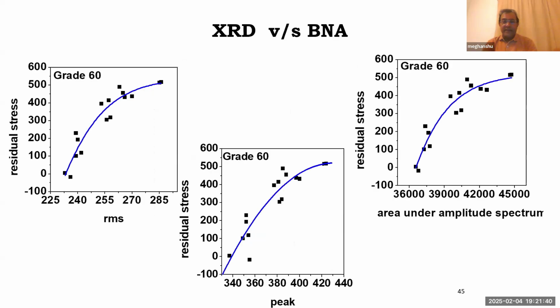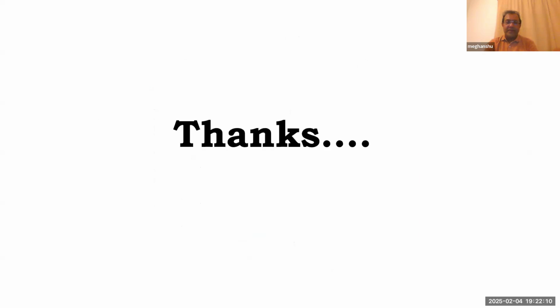So these are the various graphs between X-ray diffraction technique data and Barkhausen noise technique data. You can see that a very good correlation has been obtained between the results from the Barkhausen noise technique and the X-ray diffraction technique. So this technique has established its usefulness in measurement of residual stress in comparison to the accredited technique that you can see here.